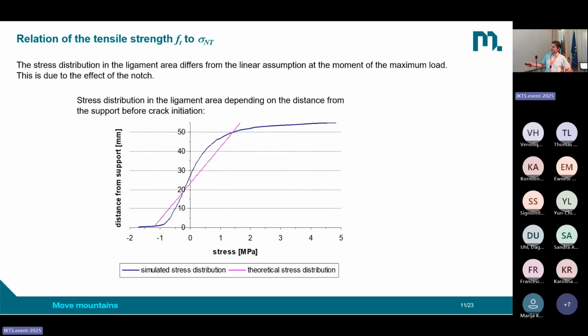And we have here in this reddish color the theoretical stress distribution according to the assumption for the nominal notch tensile strength. So this means a superposition between tension and bending. And then we have the simulated stress distribution in the finite element model. And what we see here is that there is a significant deviation between this theoretical assumption and the stress we have in reality. I say reality for my simulation because it's for sure more accurate than the other assumption, where we have a much higher tensile stress close to the top of the fracture surface.